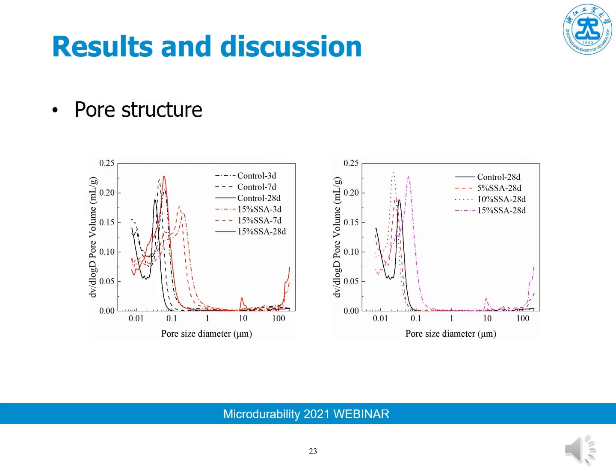This is the results for the MIP tests, and we can see the pore size distributions of the cement paste with different contents of the sewage sludge ash at different ages. And we can see that with more ash, the porosity of the cement paste increased. So this is the reason for the reduction of the compressive strength and the fracture strength, and it is also the reason for the enlarged drying shrinkage of the cement mortar.